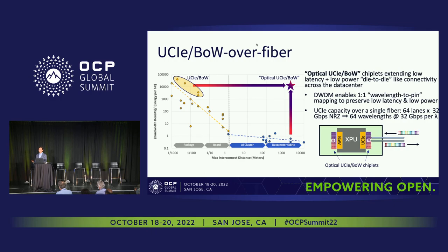Basically, the physics is that each frequency carrier is a lot more decoupled from the others as compared to a quantum well laser, and because of that, the total mode partition noise is reduced, and because of that, you can make multi-wavelength lasers that are much quieter. Maybe more physics than you wanted to hear. Okay, thank you.